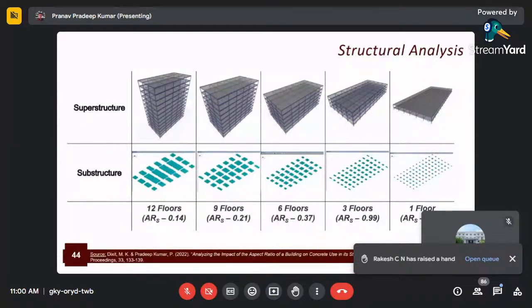This slide presents the 5 different cases that we considered with respect to the superstructure and the substructure models that were prepared, as well as the total number of floors and their respective aspect ratios. Since the aspect ratio is an inverse function of the total number of floors, we can see that as the floor numbers reduce, the surface aspect ratio value increases. You can also observe, it's not to scale, that the individual floor area here is small for the 12-floor structure, whereas for the 1-floor structure it's extravagantly big since we are maintaining the same usable floor area.